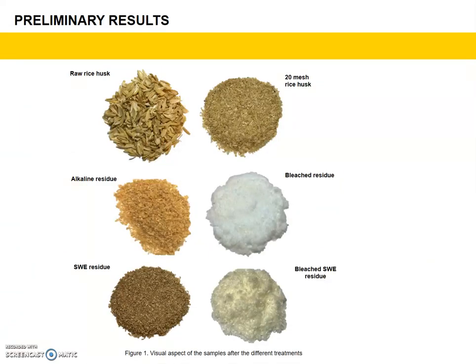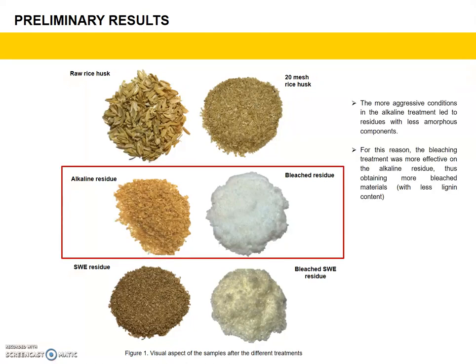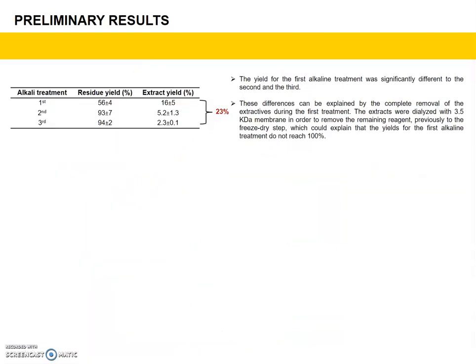After the different treatments, the visual aspect of the samples shows that the more aggressive condition in the alkali treatment led to residues with fewer amorphous components and lighter color. For this reason, the bleaching treatment was more effective in the alkali residue, thus obtaining more bleached materials, that is, with less lignin content. The yield for the first alkali treatment was significantly different from the second and the third one, which can be explained by the complete removal of extractives during this first treatment.